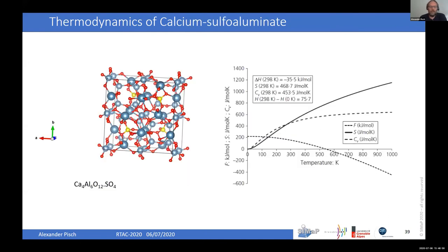So last but not least, it's the calculation of the calcium sulfo aluminate. This is a very important compound in new cements because it's highly reactive towards water. And again, only a limited amount of thermodynamic data was available. So we calculated the structure, the ground state properties. We did the phonon calculations.